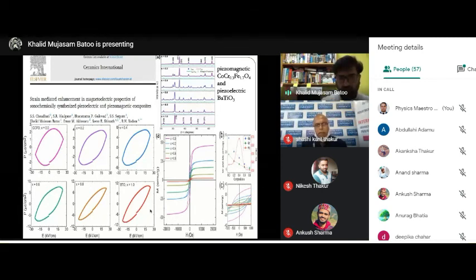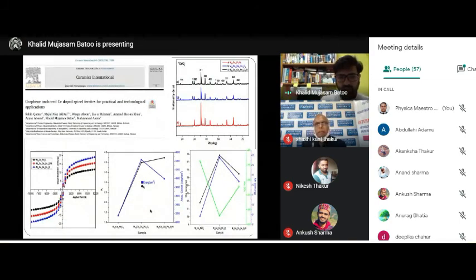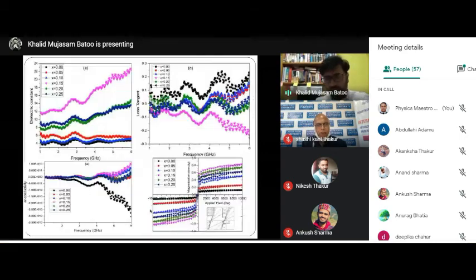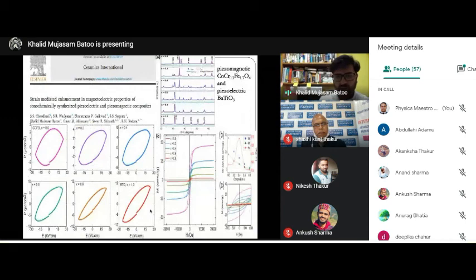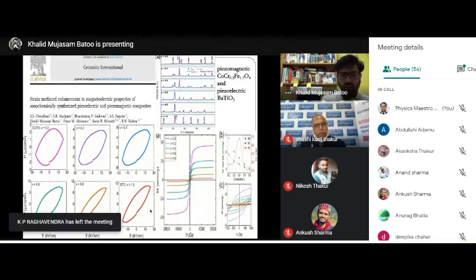We're improving multiferroic or piezomagnetic properties as we dope the piezomagnetic with piezoelectric properties. We saw the loop here, the magnetic properties, which in our earlier case were not better, they were very, very less. But in this case, the loop is saturated, the MS loop is saturated, and it is of higher value.